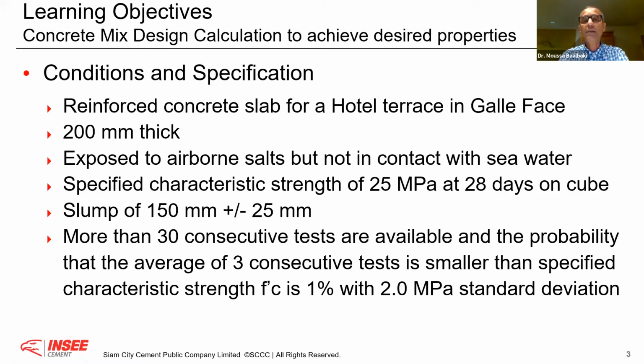Okay, reinforced concrete slab. It is a 200 millimeter thick slab, exposed to airborne salts, but not in contact with seawater. Okay, that is important to mention. The specified characteristic strength will be 25 megapascal at 28 days on cube, and the slump requirement will be 150 millimeter, plus minus 25. Now, from the statistics, there will be more than 30 consecutive tests available, and the probability that the average of 3 consecutive tests is smaller than the specified characteristic strength is 1%, with 2 MPa standard deviation.